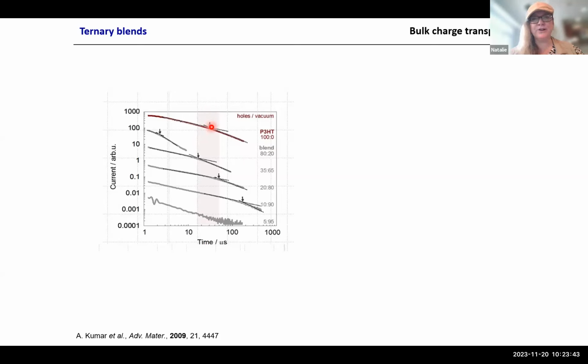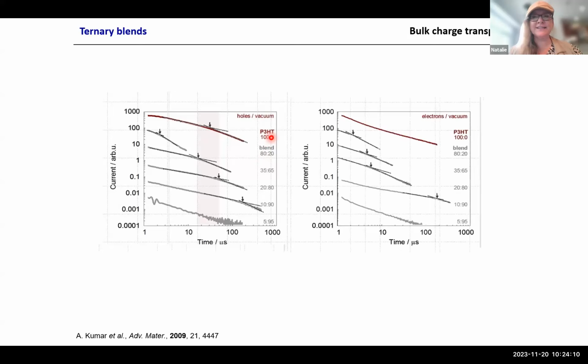And what you immediately observe is, once you add the polyethylene, here only 20%, you get a drastic improvement in the time that the charges need to get through the bulk, 5 microns. So that means the 80-20 blend sustains much faster charge transport than the neat material. And this is even more drastic when you measure electrons. The only difference is you use different electrodes in your measurement. So in the neat P3HT, we could not measure any arrival time, likely because of massive trapping. Once we do the blends, you see we get very good charge transport characteristics, unless we really go to a high polyethylene content of 95%.